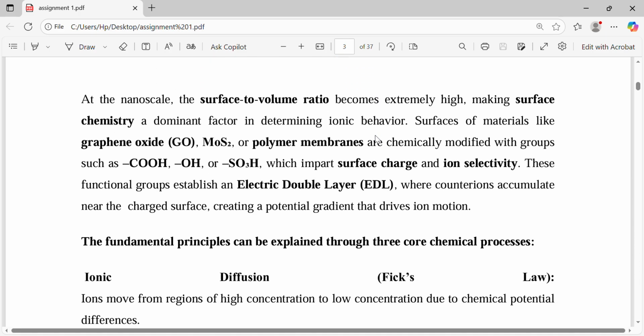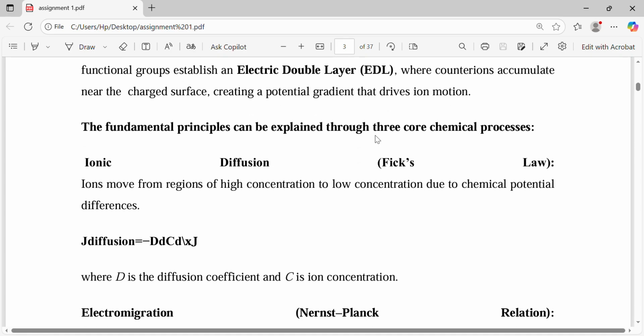At the nanoscale, the surface-to-volume ratio becomes extremely high, making surface chemistry a dominant factor in determining ionic behavior. Surfaces of materials like graphene oxide or polymer membranes are chemically modified with groups such as carboxyl and hydroxyl, imparting surface charges and ion selectivity. These functional groups establish an electric double layer where counterions accumulate near the charged surface, creating a potential gradient that drives ion motion. The fundamental principles can be explained through three core chemical processes.